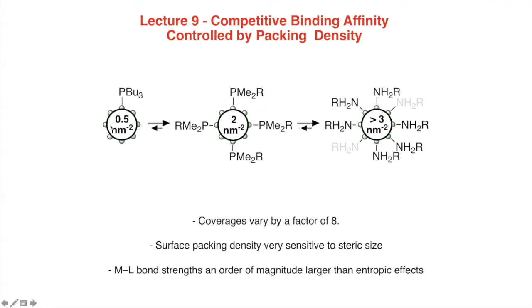Okay, and so this change in coverage, if you consider the equilibrium between these two molecules, you get twice the number of connections here, or 4 times the number of connections. And what that means is that dimethylbutylphosphine is going to way outcompete tributylphosphine for the particle surface, despite the fact that the cadmium-phosphorus bond association energies are not really going to be that different at all.